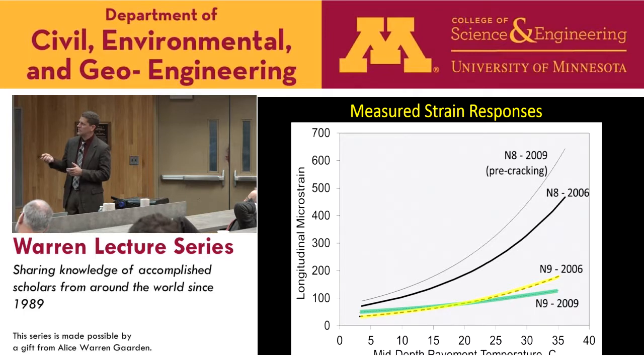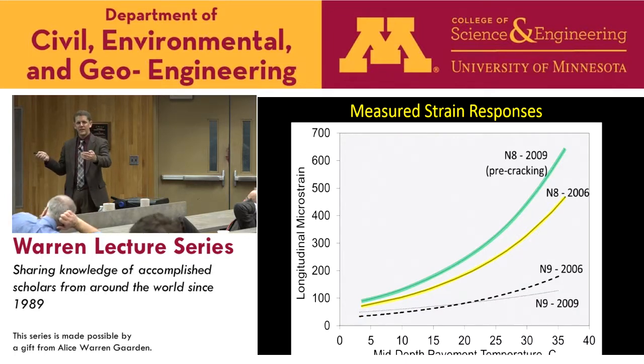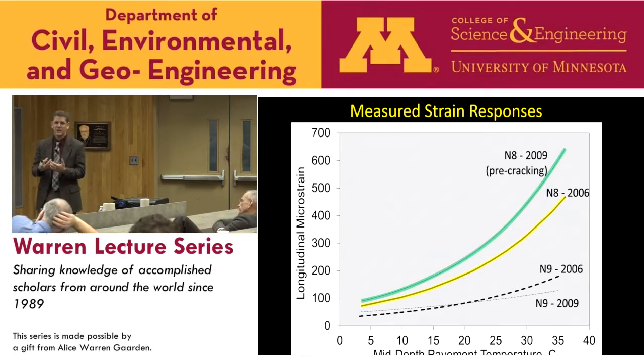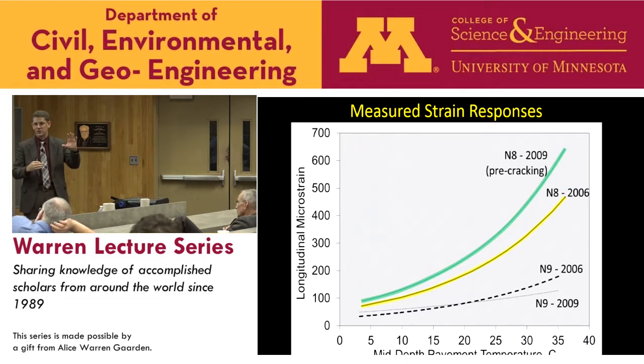What was interesting with N8 was in 06, again, we ran it to the end of the cycle, and then we did a mill and inlay. And you would think if we do a mill and inlay, it's perhaps improved the structural integrity of that structure. We should see maybe the same strain or lower. It actually increased. So what we had done really did not improve. It improved the riding surface for a short time, but in fact, we had higher strain levels. We didn't really fix the problem.